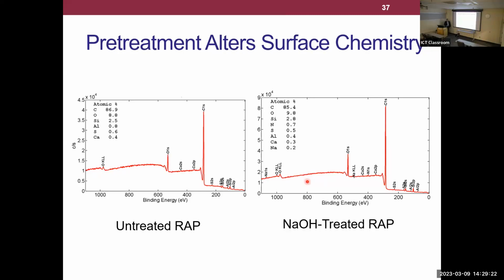So next we used something known as X-ray photoelectron spectroscopy, XPS. This is a purely surface science technique, measuring the surface chemistry only within the top few nanometers of a surface. And what we find is that we are definitely doing some sort of chemical modification of the surface. We just look at the atomic ratios here, for instance. We're doing some sort of slight modification to that surface when we're soaking it in NaOH. Again, remember, we are seeing more organic compounds after we treat it with NaOH. It's kind of doing the reverse effect that we were hoping for.